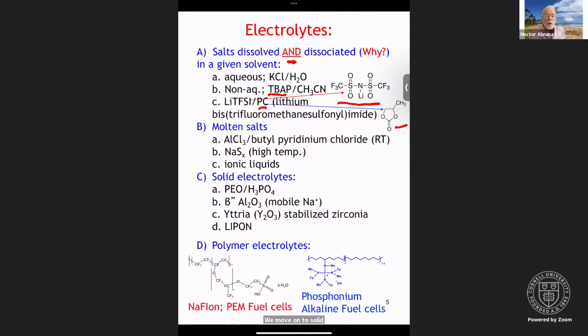So PEO stands for polyethylene oxide that has mobile protons from phosphoric acid. So-called beta double prime alumina, this is mobile sodium ions that move across that. Obviously, because these are solids, it requires relatively high temperatures. That is certainly the case for yttria-stabilized zirconia, which is used in solid oxide fuel cells. You need to go to rather high temperatures, 700-800 degrees C, to overcome the barrier to transport. LiPON stands for lithium phosphorus oxynitride, which is a solid electrolyte used in lithium-ion batteries.